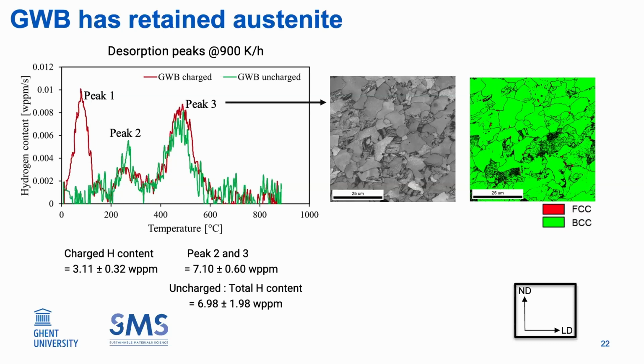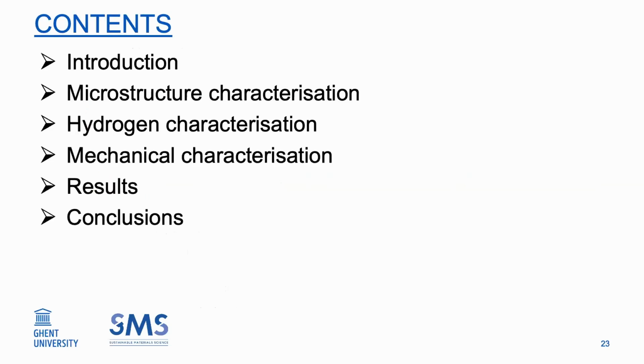Maybe other trap sites like the strained cementite-ferrite interface that is shown by peak 2, and peak 3 of the retained austenite interfaces, are all contributing to its high hydrogen uptake.